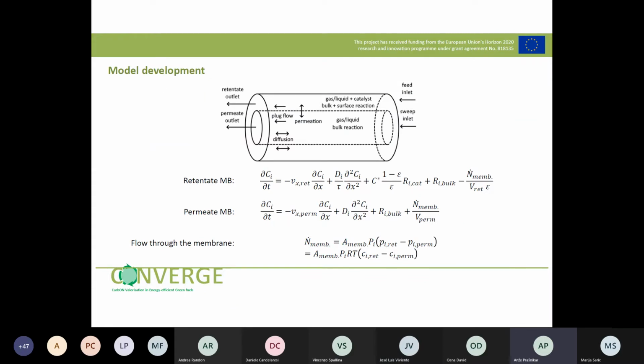So this is a scheme of a membrane module. On the right is a feed inlet. The gas enters in the outer ring of the module and passes through the catalyst layer and out on the left as a retentate. Some of the gas permeates through the membrane into the inner part of the module and exits through the permeate outlet. The mass balance equation for the retentate also includes axial dispersion in the catalyst layer since it could influence the overall activity. Flow to the membrane is correlated with the pressure difference between membrane sides. So this is this part. The reaction rates on the catalyst surface are described in the next slide.